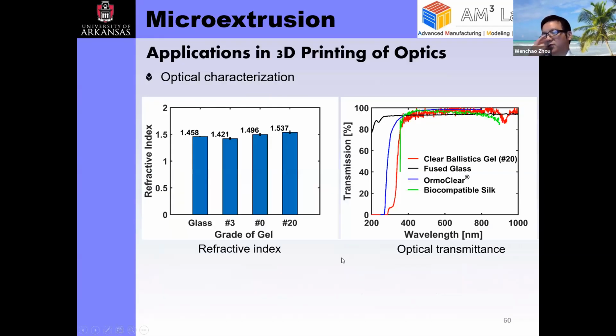But most interestingly was its optical properties. So we did some optical characterization, and this is the refractive index of glass, and it's about 1.458. And this is the refractive index of a different grade of gel, and it's comparable or even a little bit larger than glass. In terms of optical transmittance, the black line here is glass, and it has about 90% transmittance. In the visible range, the gel that we have here, this red line, can actually surpass the optical transmittance of glass, in the visible light range.